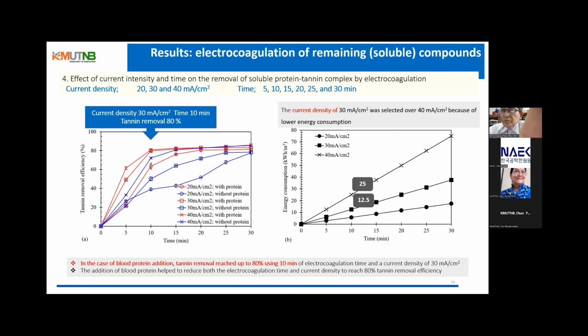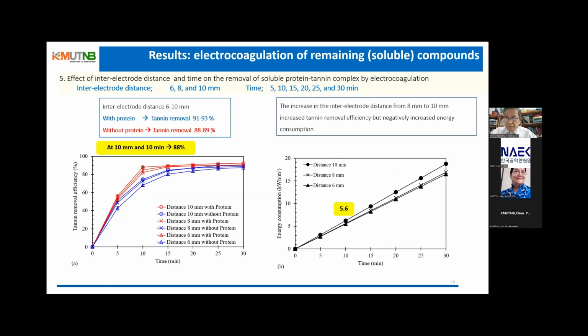It decreased the energy consumption from 12.5 to 6.3 kilowatt hour per cubic meter. And as the inter-electrode distance decreased further to 6 millimeter, the tannin removal efficiency decreased to 82%, with a slight decrease in the energy consumption to 5.6 kilowatt hour per cubic meter.